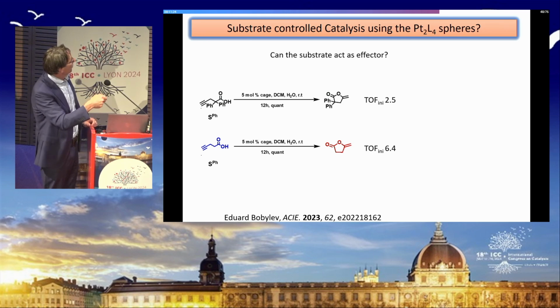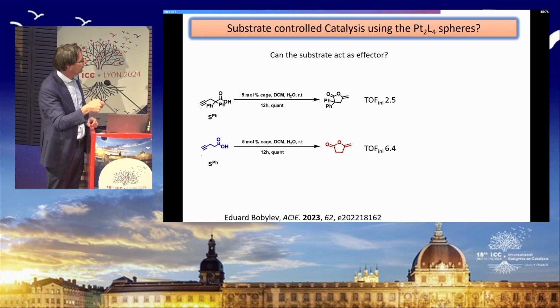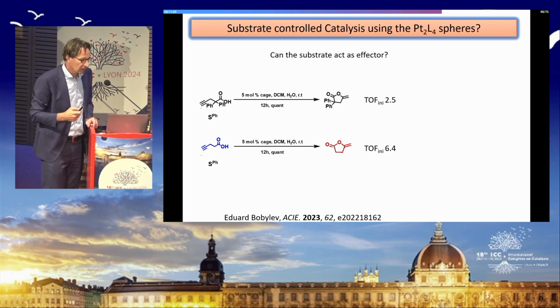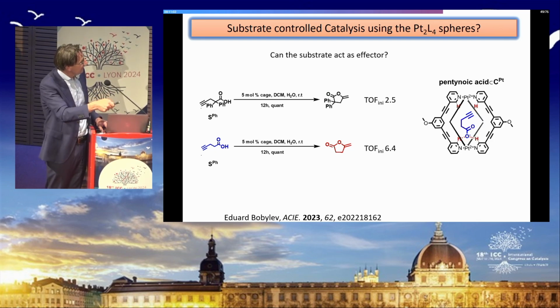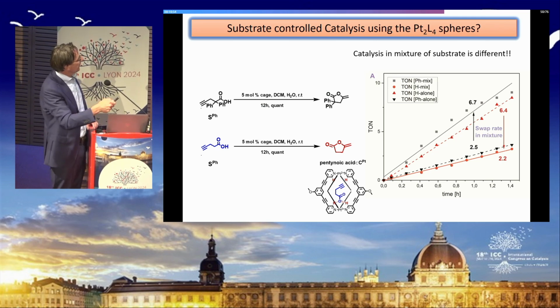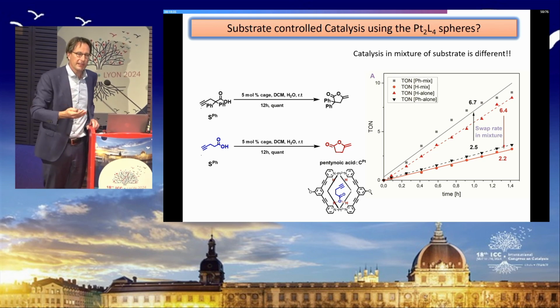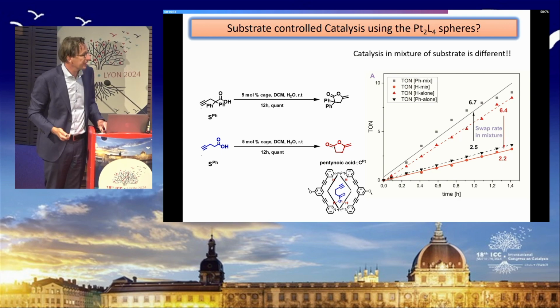Next, we compared the reactivity of this cyclization with the cyclization of this substrate, and we found that this is converting at a higher rate, which was not according to expectation, because this substrate is pre-organized. So we thought maybe this substrate acts as its own effector. And so maybe it's bound inside, and therefore it changes the rate of the formation of its own product. So we did a competition experiment where we looked at the single experiments and the experiments in a mix, and indeed we see that this substrate is converted much faster in the presence of this substrate, and this substrate is converted more slowly in the presence of that substrate, in line with the substrate being its own effector. It facilitates its own reaction.